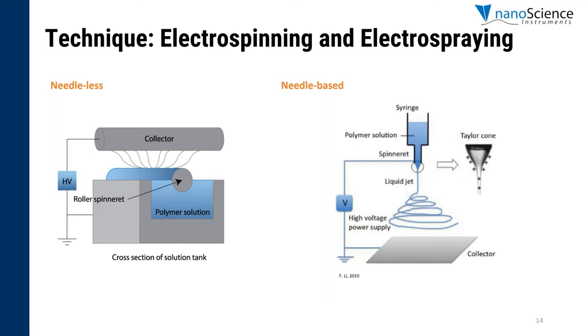From a technical view, the needle-less technique will not maintain the same concentration over time, especially if low boiling point solvents are used. For example, since we have this open reservoir, if you're not controlling that environment well, the solvent is slowly going to evaporate and the polymer solution is going to change. Meanwhile, the needle-based technique will keep the solution properties the same, allowing you to further improve reproducibility between batches. In this webinar, we will be focusing on the needle-based electrospinning and electrospraying techniques.